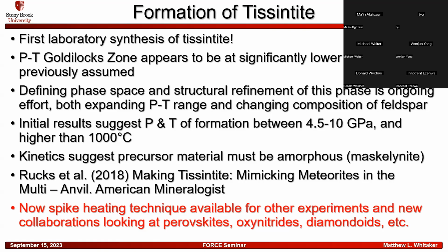So defining the phase space and structural refinement of the phase is still an ongoing effort, and we're expanding both the pressure and temperature range and working on compositional differences. But the initial results suggested that P and T formation between 4.5 to 10 GPa and higher than 1000 C are necessary conditions. And the kinetics also suggest that the precursor material must already be amorphous. If you start with solid or crystalline plagioclase, it does not go to completion. And we published this back in 2018. And this spike heating technique has been made available for other experiments and collaborations where we're looking at perovskites, oxynitrides, diamondoids, and other types of materials.